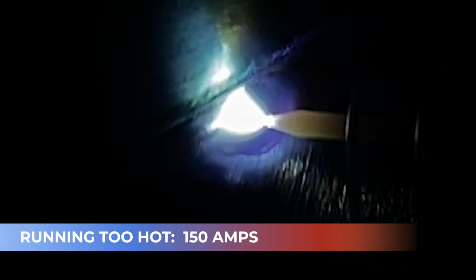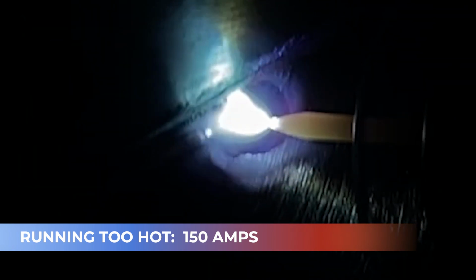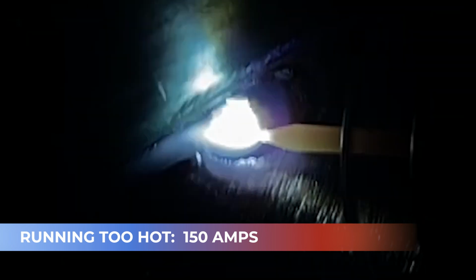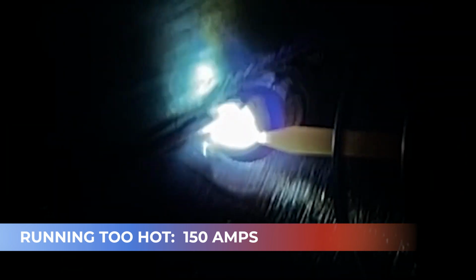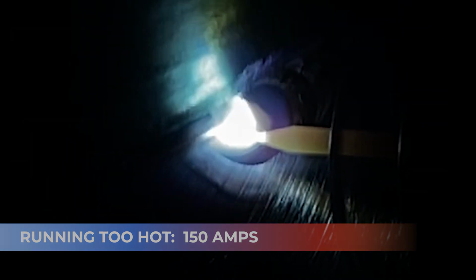And here you can tell my puddle's hot. It's dancing around like crazy. It's pulling trash into the weld. Right here, I'm running 150 amps with 3/32 filler just to simulate what it looks like when your puddle's too hot. See how it's chasing? I can't keep up with it. It's wanting to undercut on the top. Those are the things you need to be paying attention to as you're welding. Simple adjustment, go down 10 amps, see what happens.